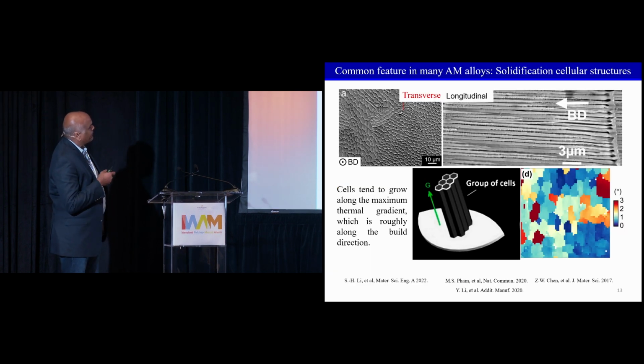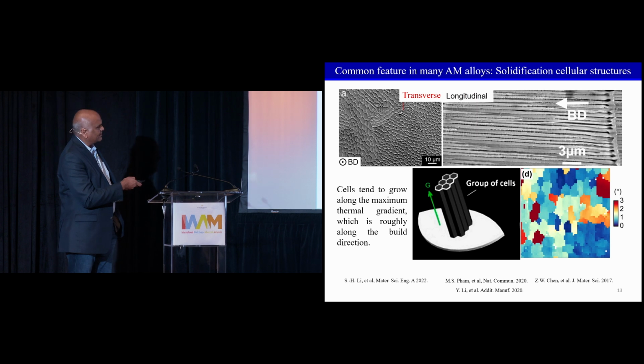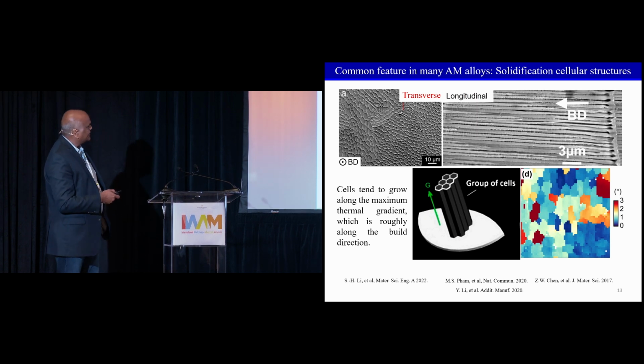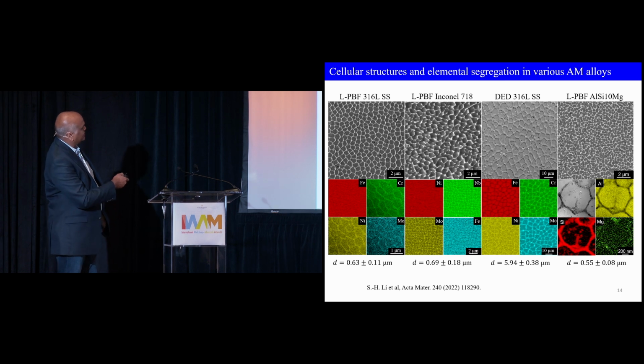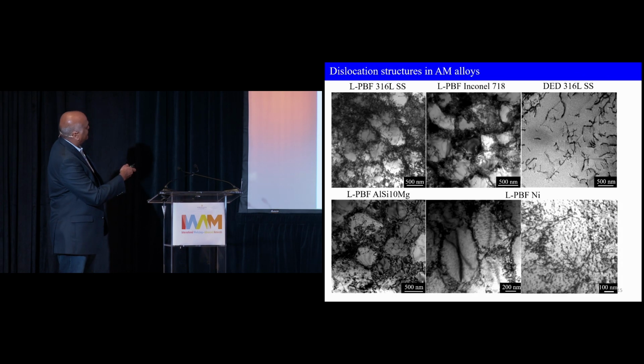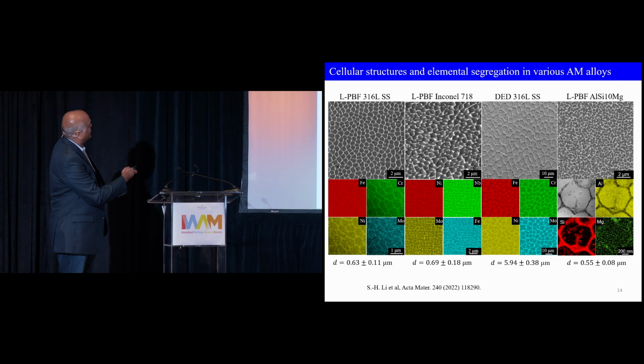One of the most common features is this cellular structure. If you look transverse to the build direction, you see these cellular structures, and if you look along the build direction, they are all aligned, with only nominal misalignment between them. These are basically solidification cells, and what happens is - let me go back. These are 4 different FCC, face-centered cubic, alloys, and you see cellular structures in all of them.